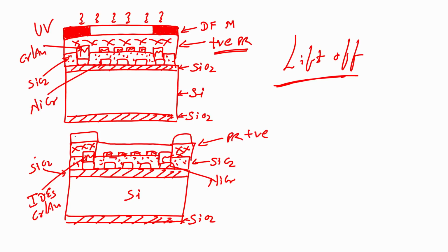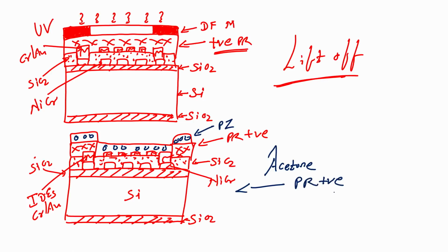So, you understand, this is a piezoresistive material, right. What I have done is, after the hard bake on the positive photoresist, I have deposited a piezoresistive material right over the photoresist. The next step is, after this I will dip the wafer in acetone. I will dip the wafer in acetone. If you dip the wafer in acetone, what will happen? The positive photoresist will be stripped off, it strips off, right.